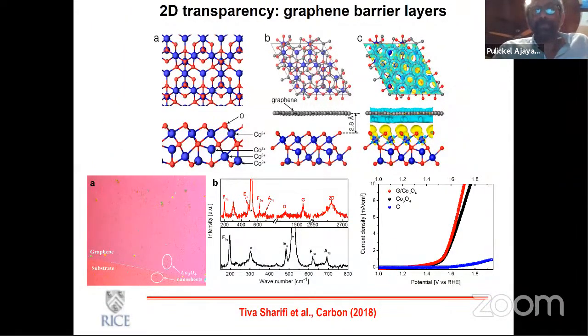Here is another example of why such thin materials are unique. Quite a while ago, we were one of the early ones to suggest that there could be a transparency of properties if you put 2D material as barrier layers. In fact, we showed that if you put a couple of layers of graphene on a substrate, the wetting behavior of the substrate can remain unchanged because there is some level of transparency, not just optically, but also in other properties. Here is another example of the same idea, that if I cover materials with these extremely thin layers of graphene or boron nitride or layers like that, you could still preserve the underlying property of the substrate or the material that is underlying.